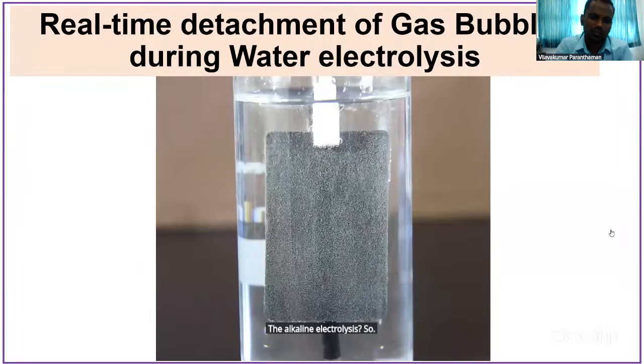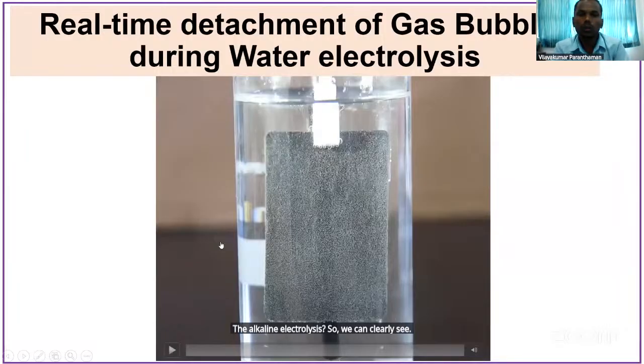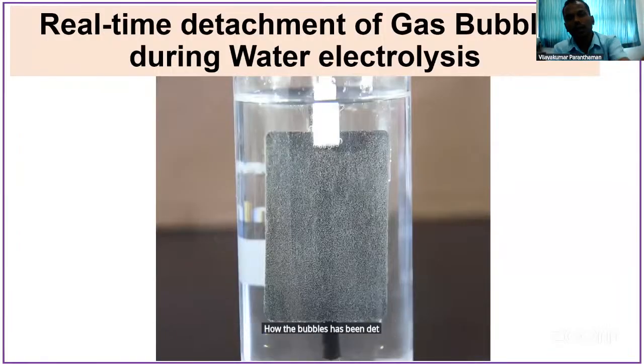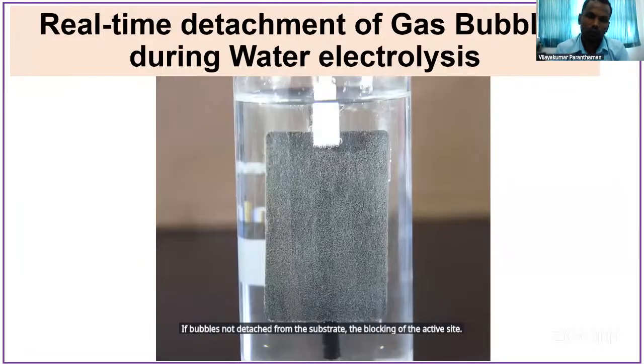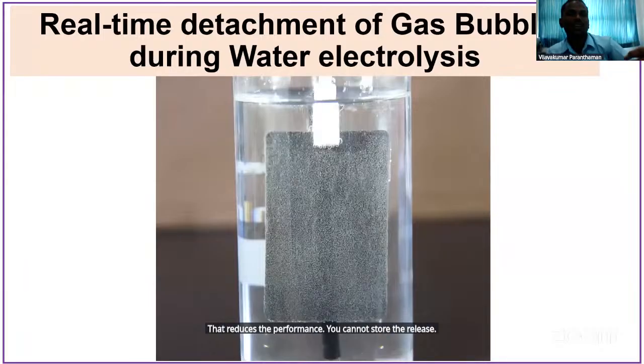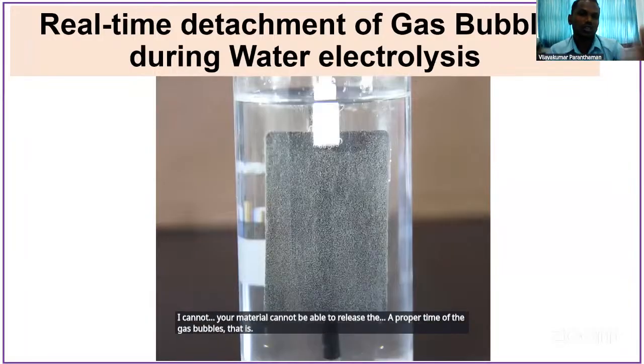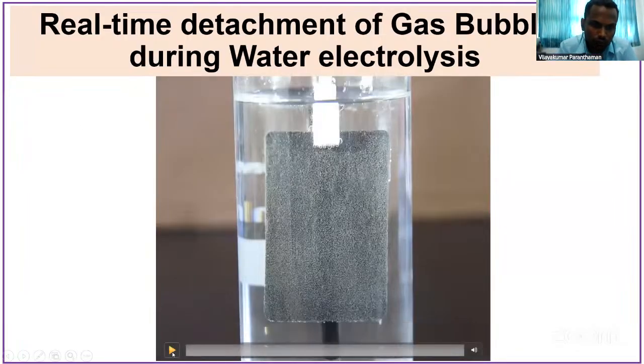So we can clearly see how the bubbles have been detached from the nickel foam. If bubbles are not detached from the substrate, the blocking of the active sites reduces the performance. If your material cannot release the gas bubbles in proper time, that is a deterioration of your total experiment, as well as the material is not good. See this video.